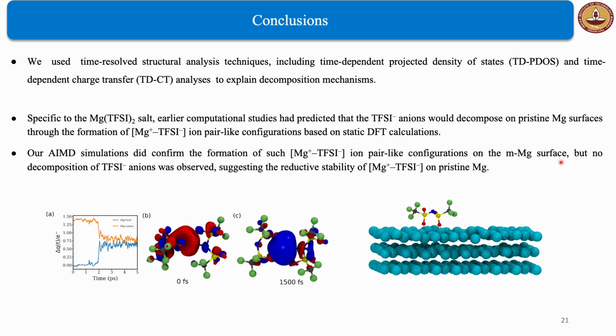We used time-resolved structural analysis techniques such as time-dependent projected density of states and time-dependent charge transfer analysis to explain the decomposition mechanism. Specific to the MgTFSI salt, earlier computational studies had predicted that TFSI anions would decompose on the pristine Mg surface through the formation of Mg+ TFSI- ion-pair-like species, based on static DFT calculations. Our AIMD simulation did confirm the formation of such species on the metallic Mg surface, but no decomposition of TFSI anions was observed, suggesting the reductive stability of Mg+ TFSI- ion pair configurations on pristine Mg.